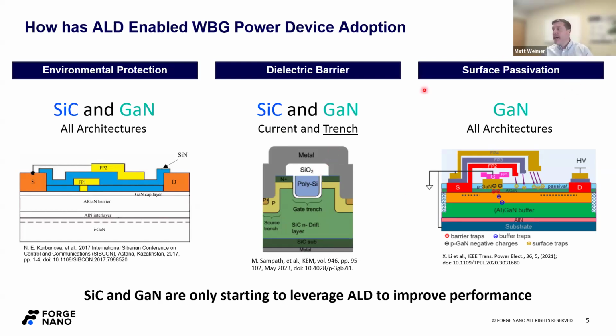Okay, and then finally, we have a unique application for gallium nitride, and I have a slide on some of the details later. Just briefly, with the architectures that we've seen, there seems to be some interface defect density that ALD can really help with. There's been some really good reviews and a lot of good research about what the identity of those defects are, and it seems like ALD has some good alignment with removing some of those. From our understanding, this is already used in production. There was a lot of work at IMEC to develop this and push it forward.